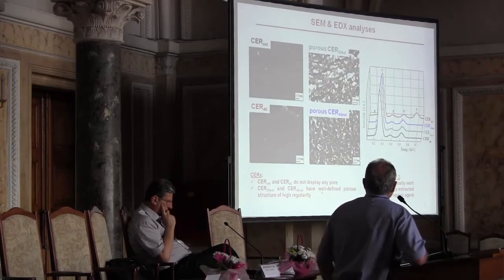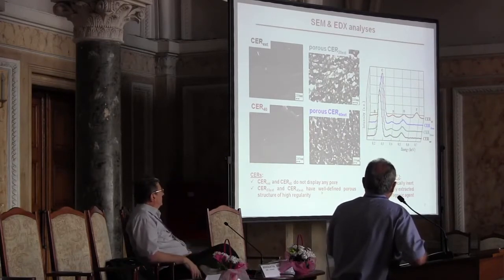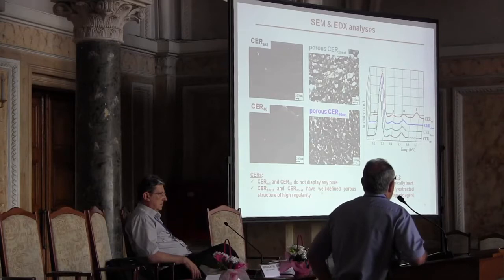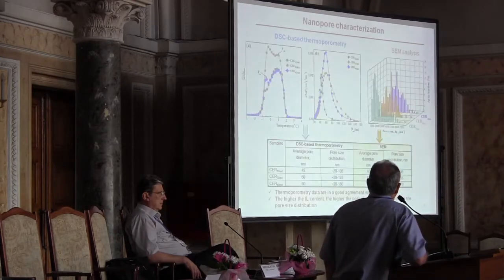And this is a combination of SEM and EDX analysis. You can see microphotos on the left. It's precursors, and on the right is nanoporous films. You can see pores in the figures. And EDX analysis also confirmed that ionic liquid was completely removed because no traces of boron or fluorine were found in the final polymer network after extraction of ionic liquids.